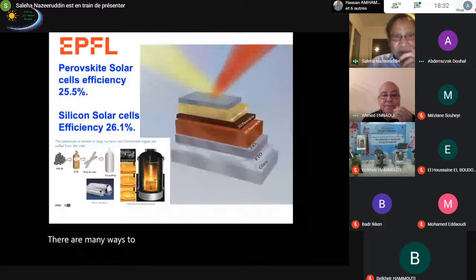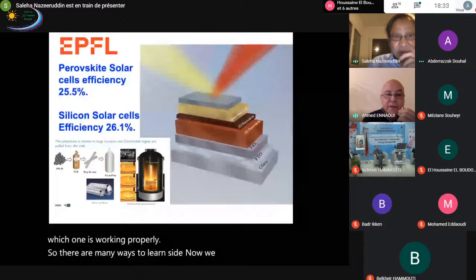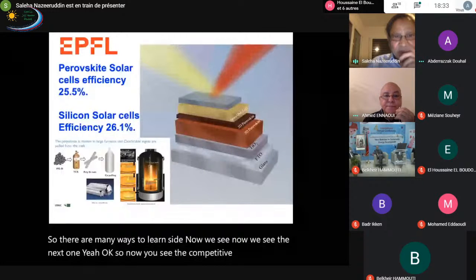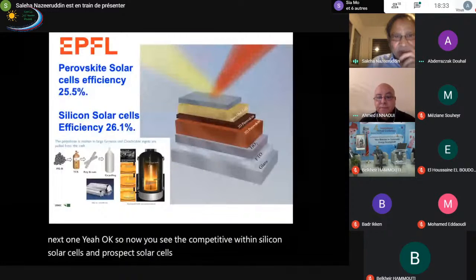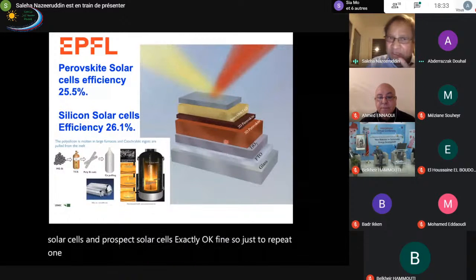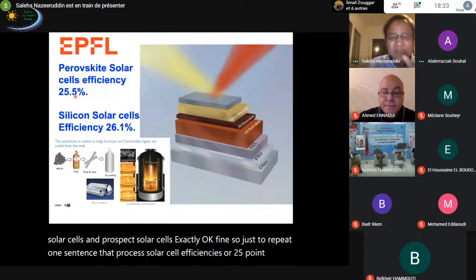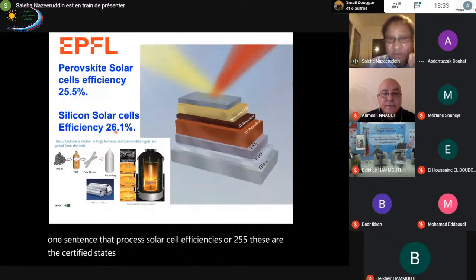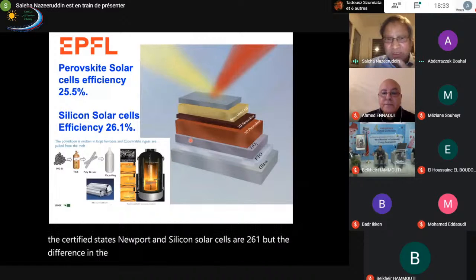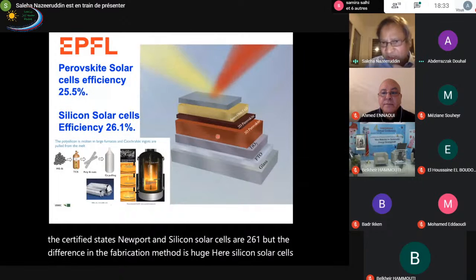Now you see the comparison between silicon solar cells and perovskite solar cells. I just repeat one sentence: perovskite solar cell efficiencies are 25.5, certified at NREL, and silicon solar cells are 26.1. But the difference in the fabrication method is huge. Silicon solar cells require high temperature; perovskite solar cells require 120 degrees temperature.